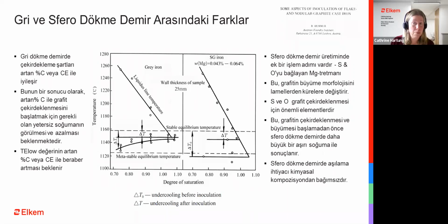So as a result of this, it is expected to see a decrease in undercooling needed to initiate graphite nucleation with increasing carbon in gray iron. And TE low as a result of this will also increase with higher carbon and higher carbon equivalent. So ultimately, a high strength gray iron will typically have lower carbon content or carbon equivalent, and will therefore have more undercooling because you are more to the left in this diagram, versus the gray irons that should transport a lot of heat, like the brake discs, or have a high damping capacity. They will typically have higher carbon equivalent and will also have a better nucleation condition to start with compared to the high strength gray irons.